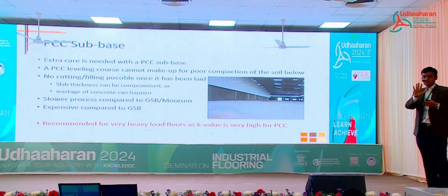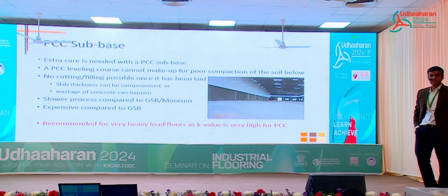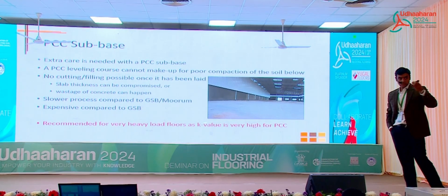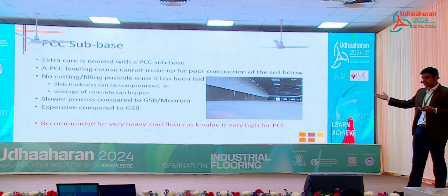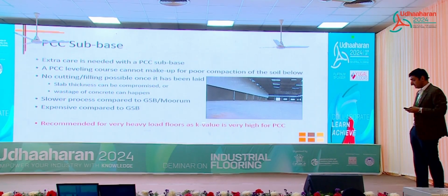But the biggest advantage of PCC, which is important to share, is it gives you the highest K value. It is the stiffest spring you can manufacture. So where you have very heavy loads, sir talked about ASRS floors, clad racks, where you're talking about 20 ton, 30 ton point loads, there PCC gives you that extra support that your slab needs. So it's good to have there.